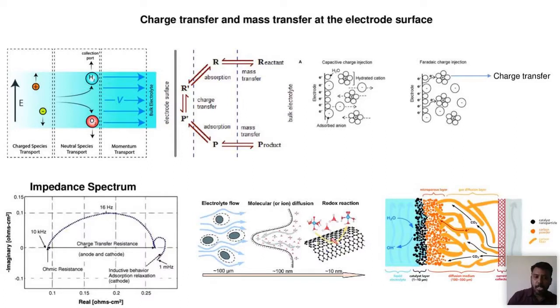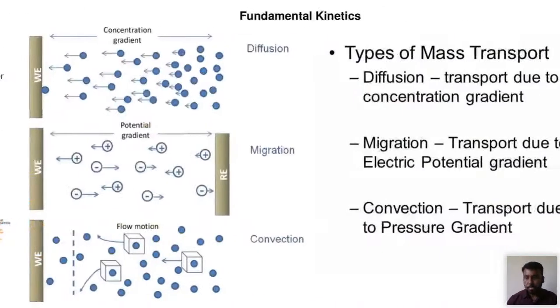Also, in some cases, you can observe some inductive loop due to the adsorption of the intermediate. Other than this process, electrolyte flow, molecular ion diffusion, and redox reaction can also happen. So we have to bear in mind all these things when dealing with electrocatalytic reactions. In this picture, you can observe the transport of the electrolyte species, for example carbon dioxide and also water molecules, through the porous substrate. So if you have a porous surface, then the transport will be much more efficient.